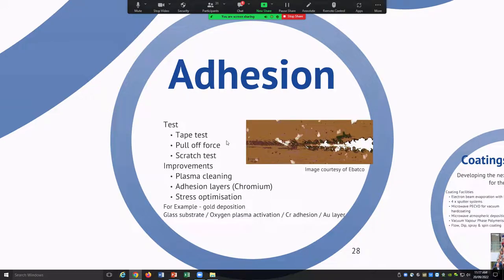I'll finish up on adhesion, and this is probably an example of how complex just a simple sort of thing can be. Obviously, everyone wants to have their coating stick in the right place and time, so we need to measure it. We use a tape test, literally. We put a bit of sticky tape over our coating and then we rip it off. If the coating stays behind, that's a good start. We can get more elaborate. We can do a pull-off test or we can do a scratch test. But first pass, a bit of sticky tape on your coating is a good start.